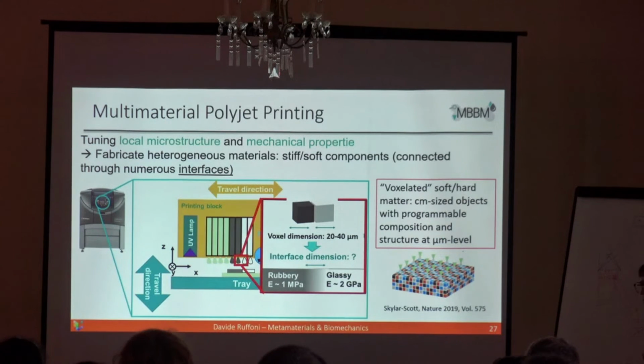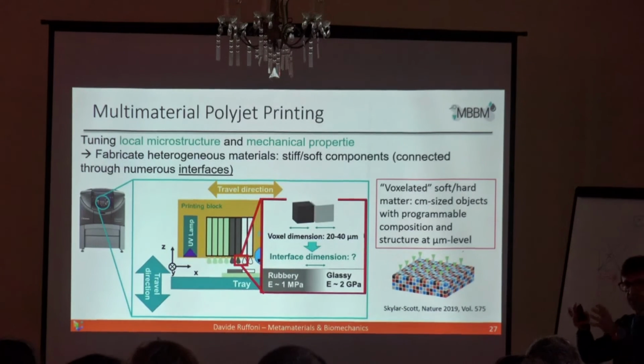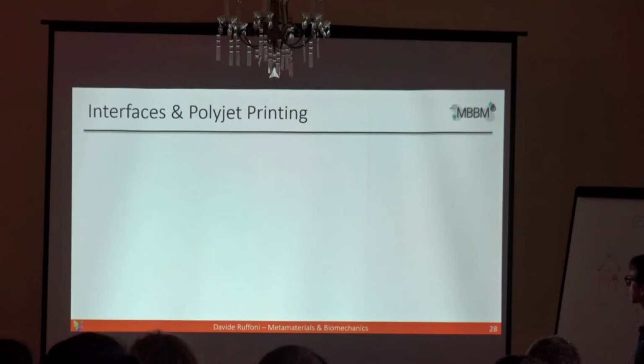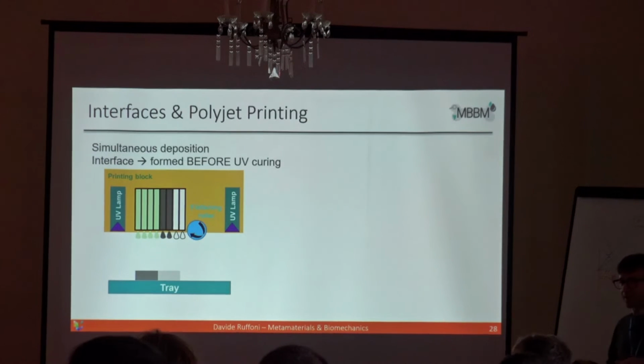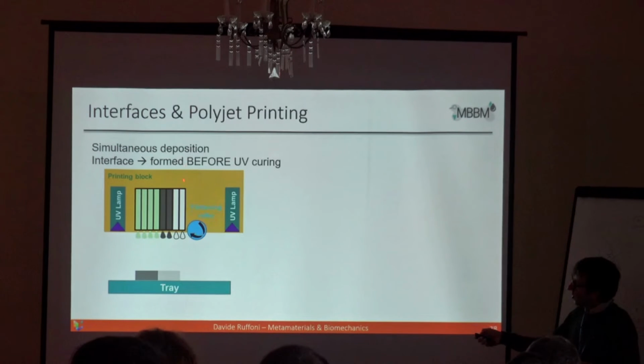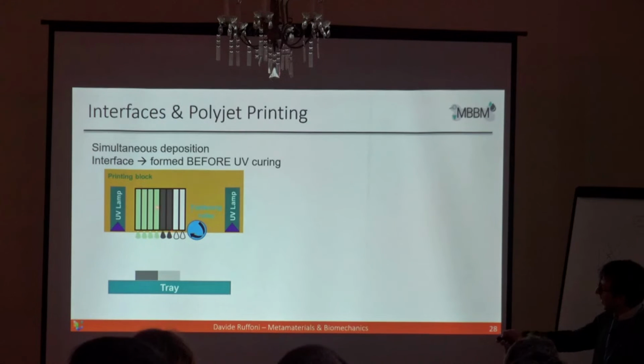But before starting to work with this technique, we got interested in the interfaces between different materials, because you can imagine that if you have different materials, there are interfaces between them, and we are interested in the properties of those interfaces. To make it very simple, as a function of how you are printing your objects, there are two types of interfaces. If you are depositing simultaneously stiff voxels, in light gray, and soft voxels, which are dark gray here, before curing the system with UV light, the interface is formed before UV curing. So the two materials come in contact with each other before curing.